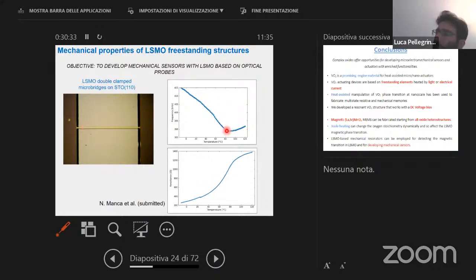And in this region where you have the resistance change, you also have a change in the behavior of the frequency due to the change of tensile stress. At low temperature, we argue that this is due to the change of the Young modulus by this kink, and above this temperature it is probably a combination of the change of Young modulus and the change of thermal expansion coefficient of the films with respect to the substrate. The details will appear soon, as we recently submitted this article.